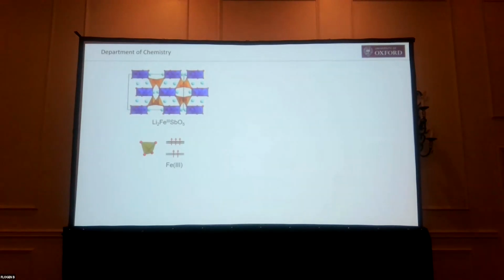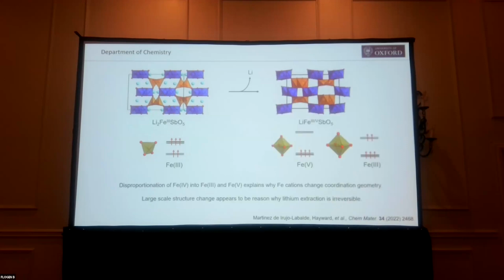We also don't think you can stabilize high oxidation state iron in materials where you take out lithium. So we make this state here, which is an iron 3+ state with a slightly different structure. And we can take out lithium chemically, and again, we get the iron migration from a tetrahedral to an octahedral site. But this formally iron 4+ phase disproportionates to iron 3+ and iron 5+, which then stops you putting the lithium back in again. So this is the thing. The initial things we looked at really weren't very encouraging.